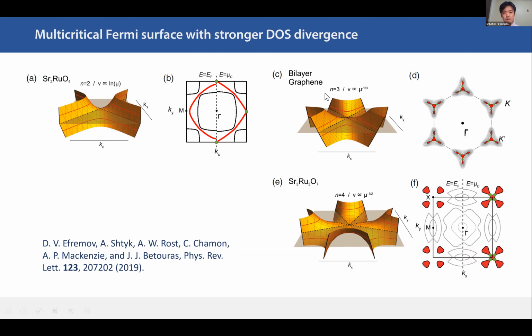So, for example, in bilayer graphene, three Fermi surfaces touch at a point, and this results in a stronger divergence than log. In this case, this gives rise to a divergence with the power of -1/3. And when four Fermi surfaces touch at a point, this gives an even stronger divergence with exponent -1/2.